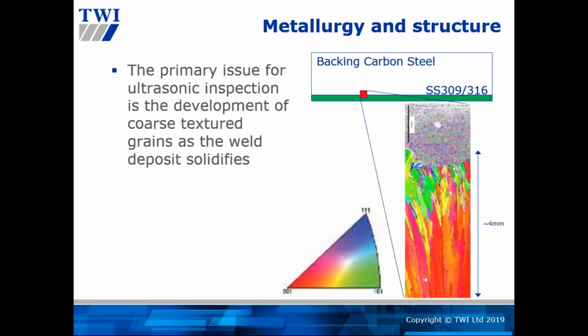The primary issue for inspection is the microstructure that develops during the weld overlay deposition process. Here I have a diagram that depicts typically a carbon steel backing, which could be a vessel or a pipe, with a two-pass deposition of a CRA layer, in this case a 316 stainless steel. What you can see is the difference in microstructure between the carbon steel and the cladding, and the large, coarse textured grains that develop in the cladding are the primary reason for the inspection issues that are often but not always encountered with these types of components.